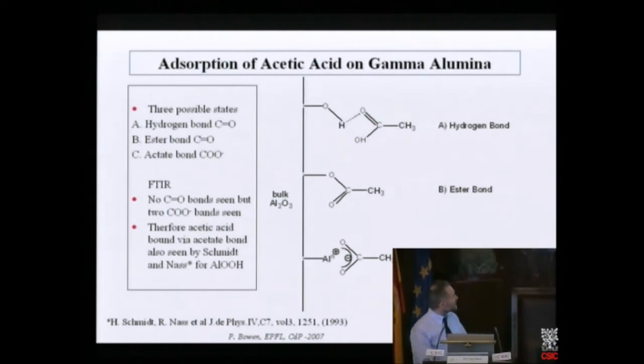And from infrared, we can see that, in fact, it was attached via the acetate group. So it's much simpler for molecules. If you have polymers, then the adsorbed conformation is a little bit more difficult. So if you can use something simple to disperse your material, you just have to choose the right chemistry such that your molecule adsorbs on the surface. Theoretically, it's very simple. With these calculations, you can estimate what you need.